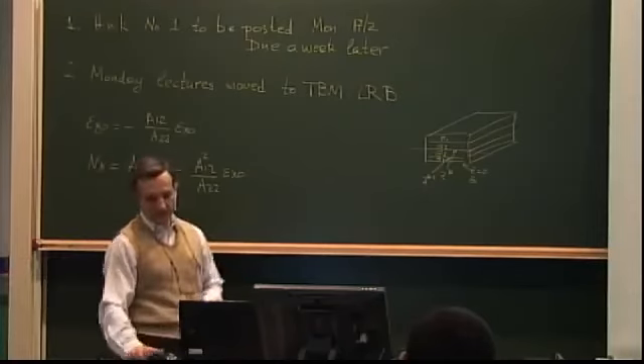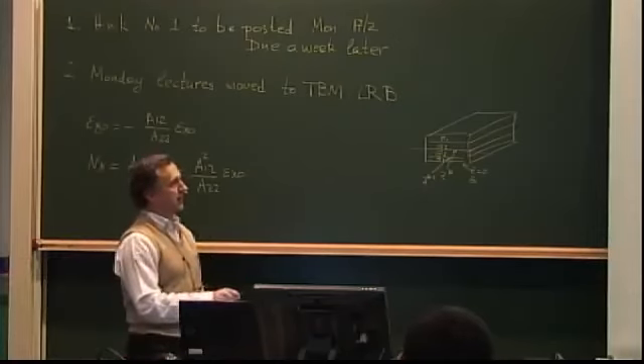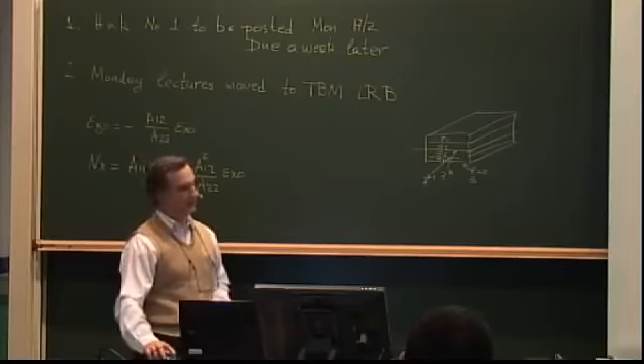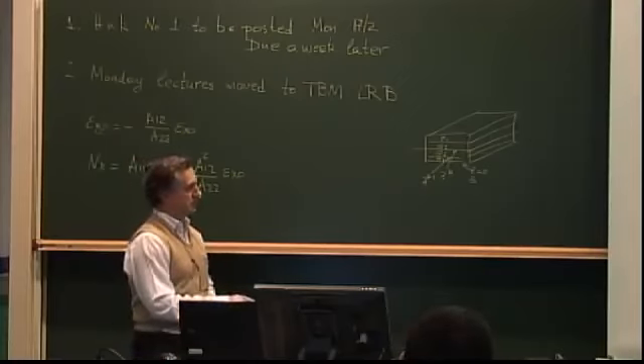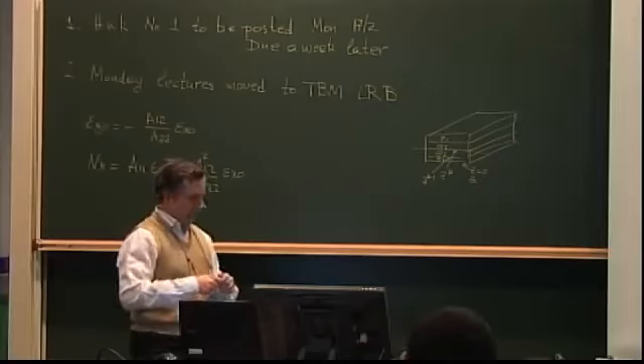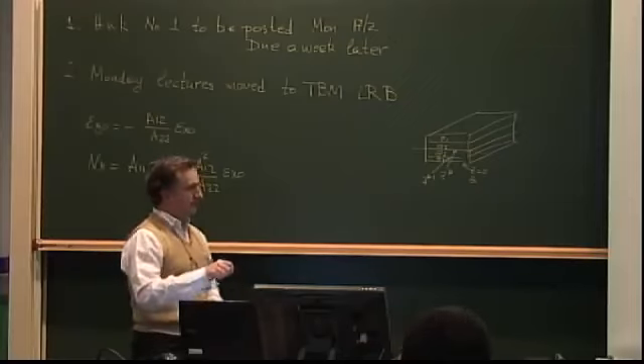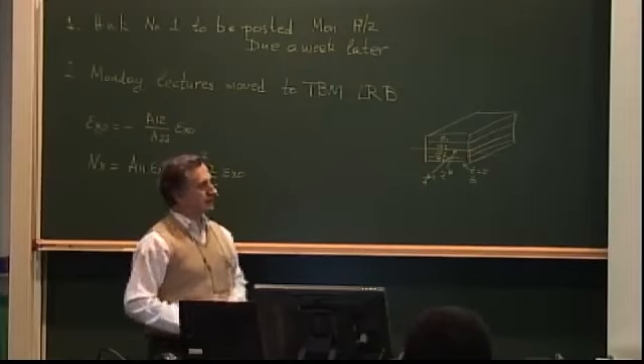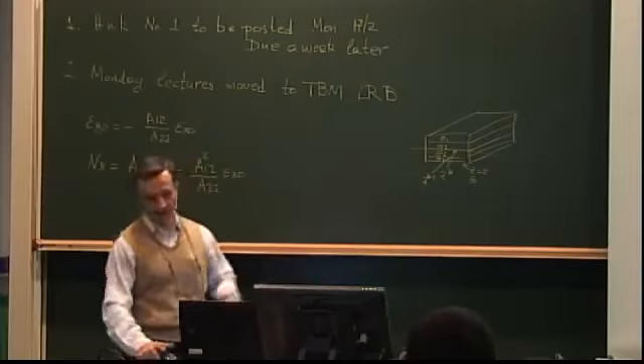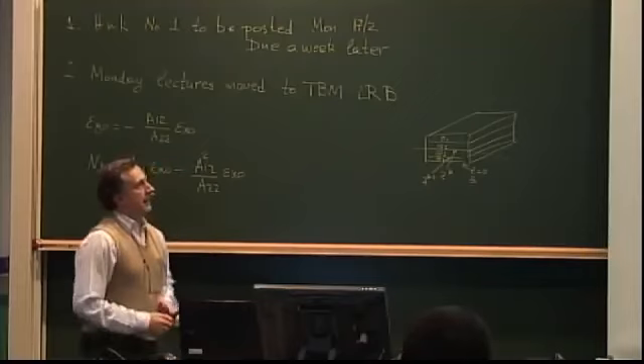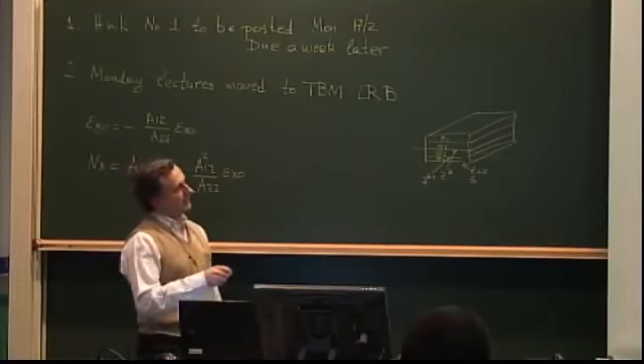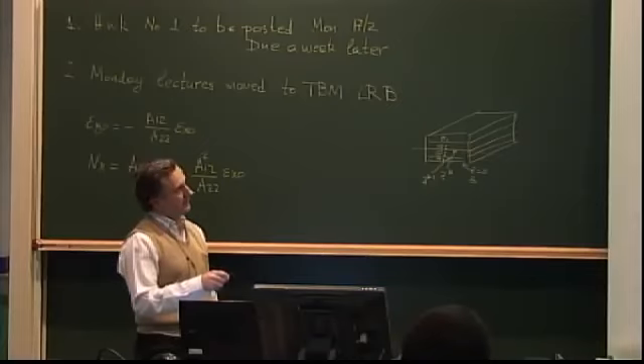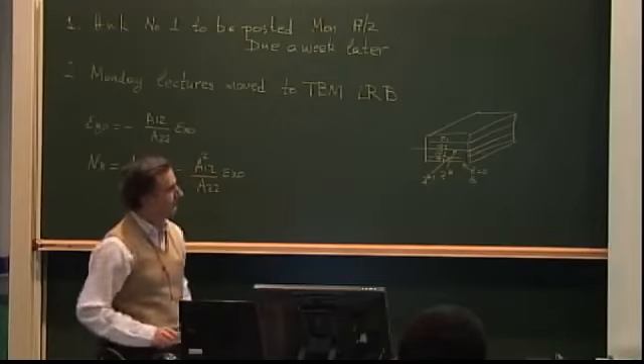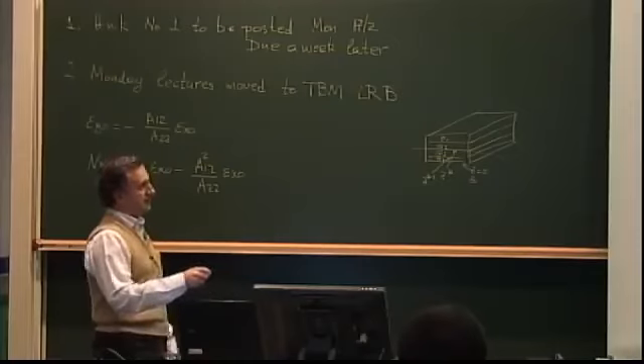And we know that stress and strain related through a constant coefficient means that that constant coefficient is the Young's modulus. So my Young's modulus for this laminate is given by this quantity, which involves directly the A matrix. And you can also show that the quantity here in brackets is actually the 1 over little a11. So the inverse of the A matrix involves this little a11 term.